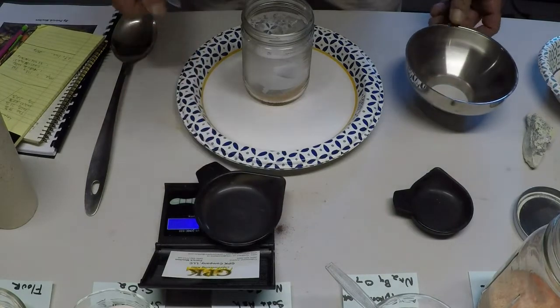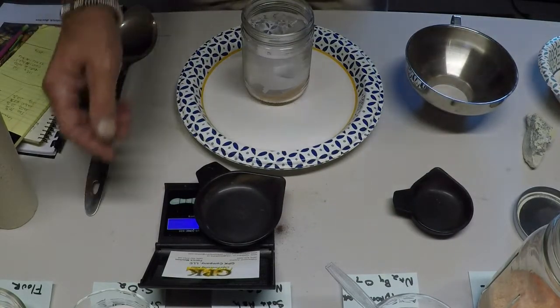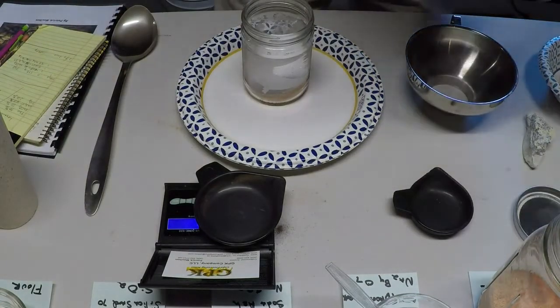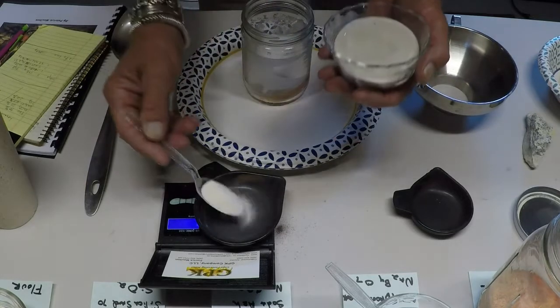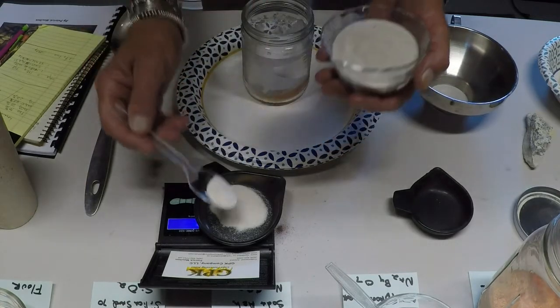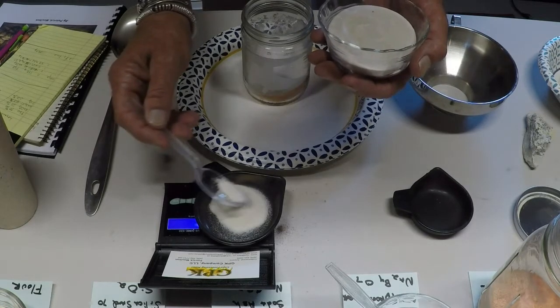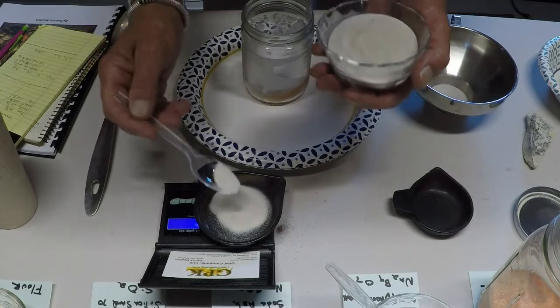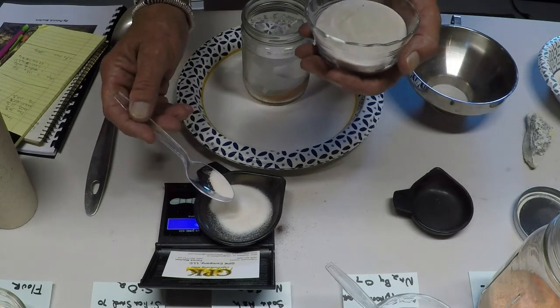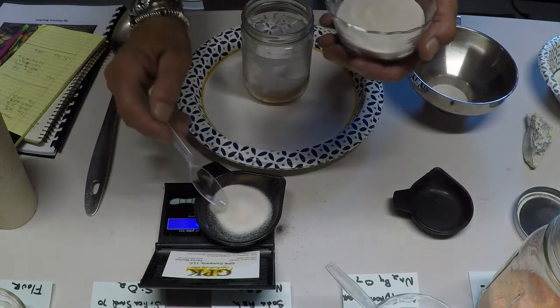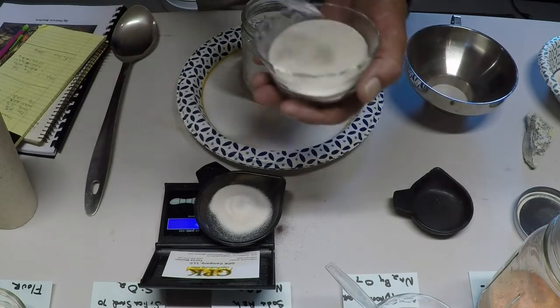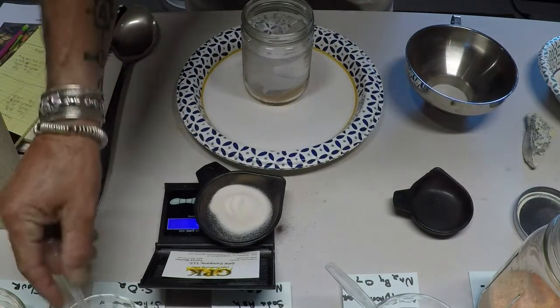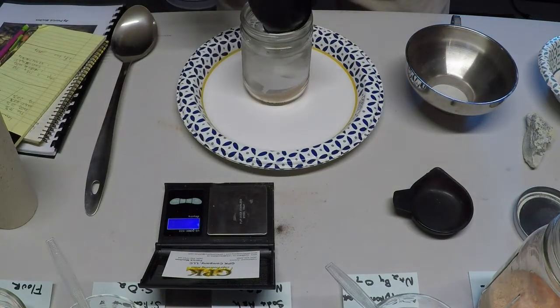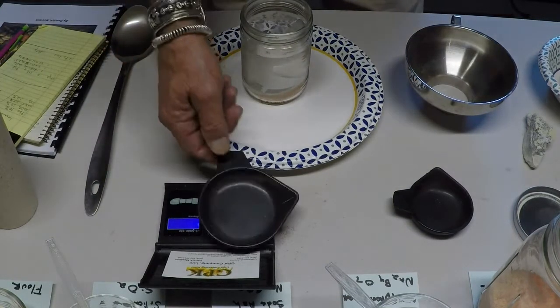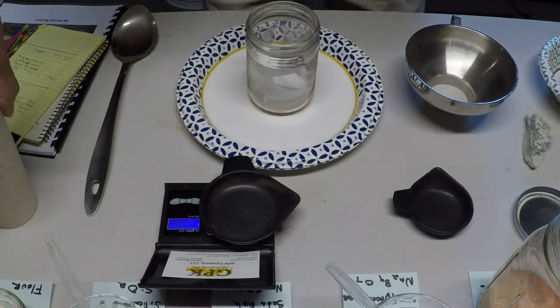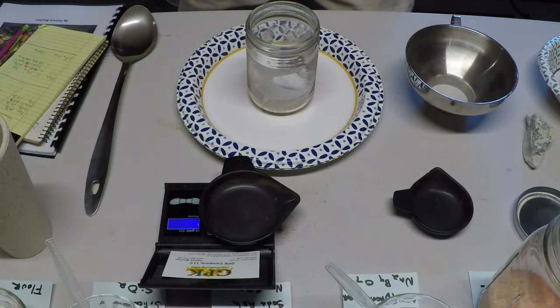Now silica sand, SiO2, I need to add 15.6 grams. And silica is pretty dense, so it's not going to amount to a whole heck of a lot in here. 15.6. Each one of these components performs its own little role during the crucible fusion, and each one of them is very important. So that's the constituents of our flux right there. That's what's going to go into our 40-gram crucible, into the furnace, the KK8.